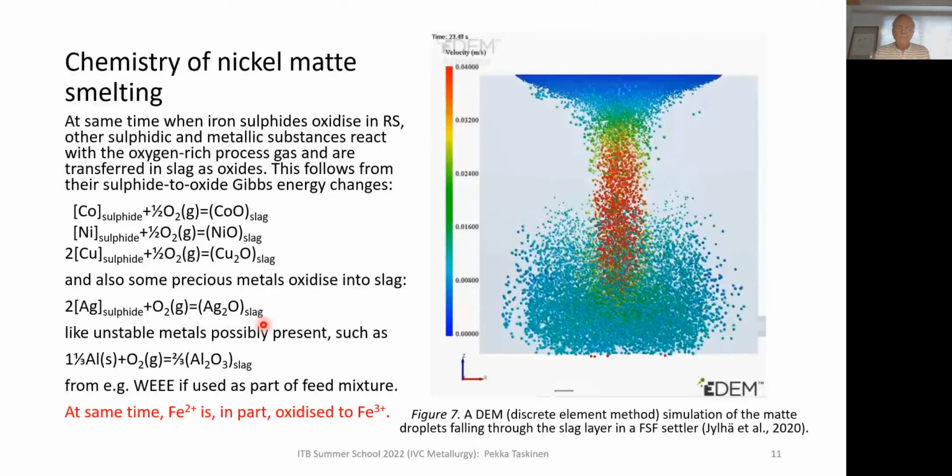And this is scientifically important because for many years we believed that the chemical dissolution, for example, of platinum is not possible because of the very low stability of platinum oxide.